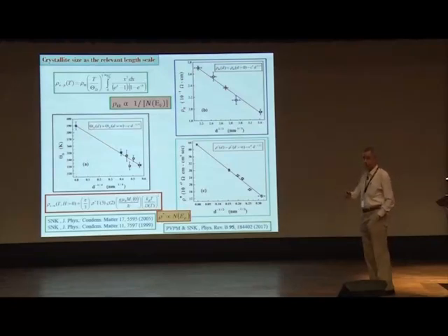When you are decreasing the size, the surface area is increasing, and so is the surface disorder. Because of that, the density of states curve is getting more and more smeared out, so the density of states at the Fermi level is getting suppressed. The sharp peaks near the Fermi level are getting leveled off, so the average density of states at the Fermi level is decreasing.